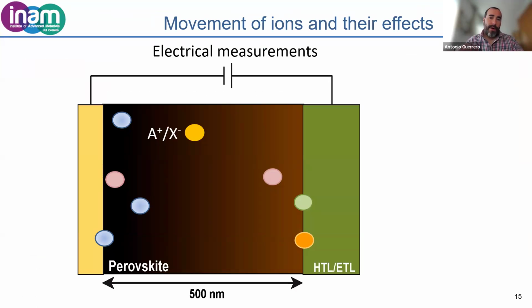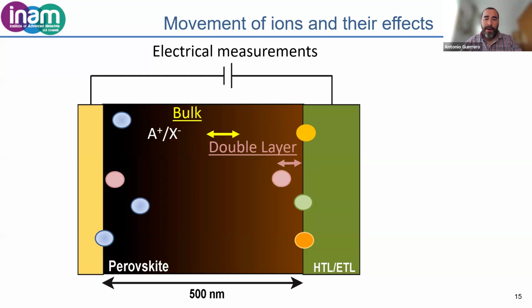Once we apply an electrical field, the A cations and the X anions can migrate following the electrical field. And these ions can migrate from the bulk of the perovskite and go to the contacts. We have been characterizing this migration using the electrical techniques that I mentioned. I will show you one example later. We can, for example, characterize how these ions that come to the contacts generate a double layer of ions. And this is very important because the perovskite is a very soft material and it behaves as if it was an electrolyte.